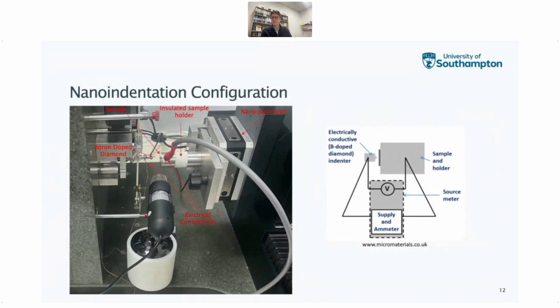So looking a little bit more in detail about the actual configuration that we use in the nano-indenter. This is our nano positioner stage here on the right, and then we will horizontally mount the sample on the sample stub, which has an insulating sample holder here, so a hard polymeric material or PEEK, for example. We have our sample mounted at the end of that, and then opposite is the boron doped diamond tip, and then we have some electrical contacts coming out the back of that and also completing the circuit to the sample holder. And so this is the four-terminal configuration that we have, where we measure the voltage and we have a supply and also measuring the current within that as well.